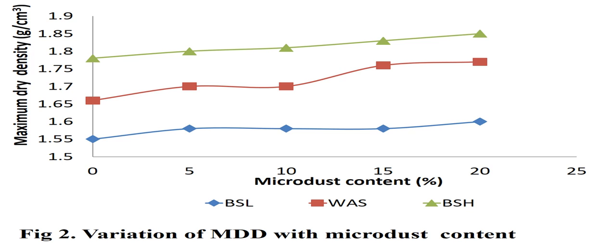And also possible cation exchange processes which produced friable flux, and production of such flux makes compaction expedient, and therefore it is possible to impart higher energy to the soil during the compaction. So these are the things that possibly cause the increase in the maximum dry density observed.